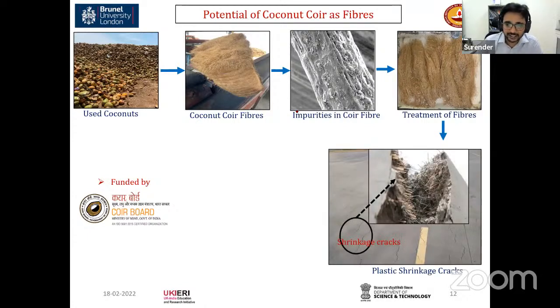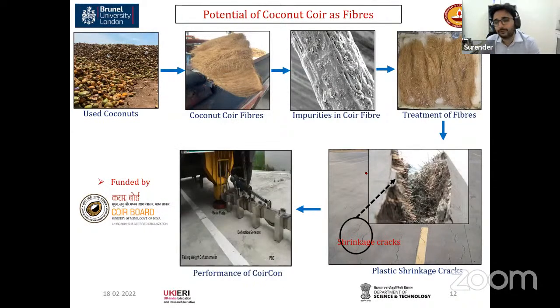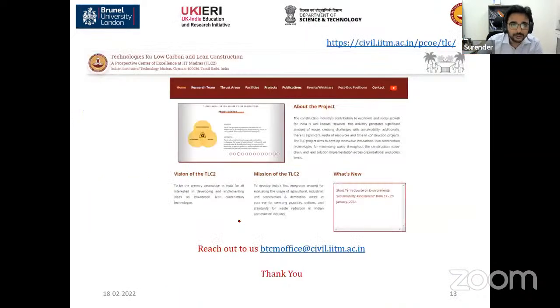But for pavement applications, because a pavement has a large exposed surface area, plastic shrinkage cracks are very, very crucial, right? It always happens. So if these fibers, even in a small amount, are able to address the plastic shrinkage cracks, then it will be very, very good. But if you are using these materials as a biodegradable material, it may affect the performance of the concrete. So we're also evaluating the performance of concrete containing the coir fiber, so as to improve its potential. So with this, this is my last slide.